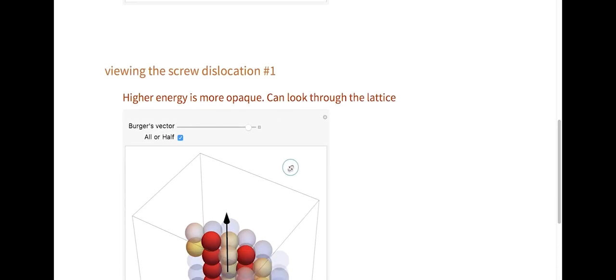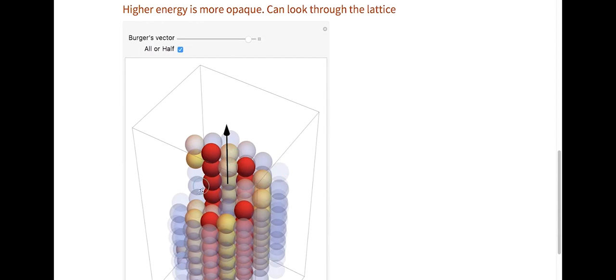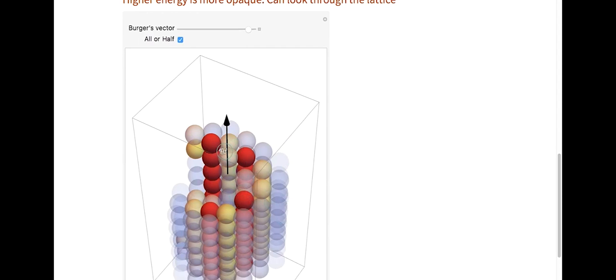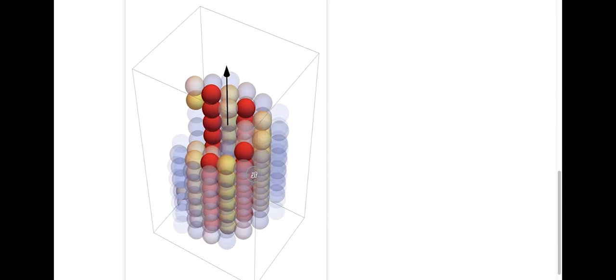So let me go down here where I've colored my particles also based on opacity. And you can really see the super high energy opaque red lines near the center where my dislocation is. And this is a pretty cool result of simulating screw dislocations. I expect energies to be higher right around the dislocation, which I saw pretty clearly with the cubic lattice. But in HCP, in addition to energies being higher, energies become a lot higher a little ways away. So this is a neat example of how simulations can really teach you something more about a system that you didn't know before.